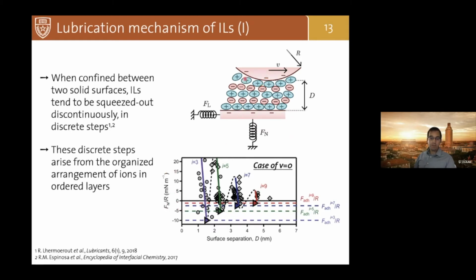Here you see the force experienced by the surface when they come into contact with the reference surface here, the bottom one, as a function of separation d. And what you see is exactly some fluctuations. These fluctuations, or discrete steps, correspond to the squeezing out of ionic liquid during the progressive decrease of the separation between the two surfaces. So in other words, the ionic liquid organizes itself in layers where you have an excess of cations and an excess of anions. And when you're decreasing the separation, you're progressively squeezing out slabs, electroneutral slabs, so you're removing anions and cations at the same time. And because of this squeezing out, you have these progressive, discrete steps in the force separation curve.